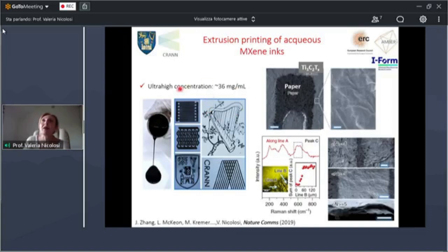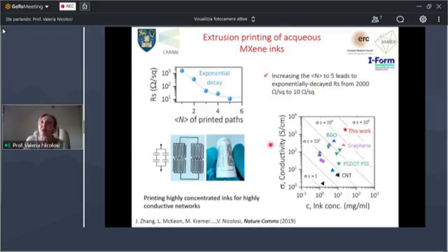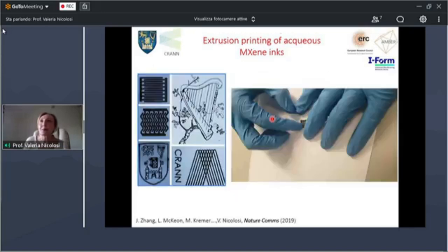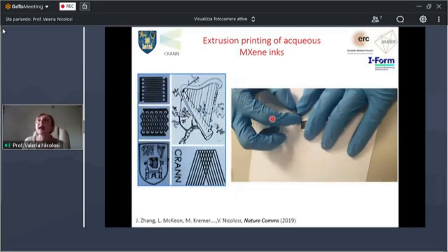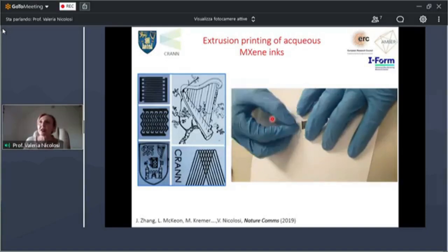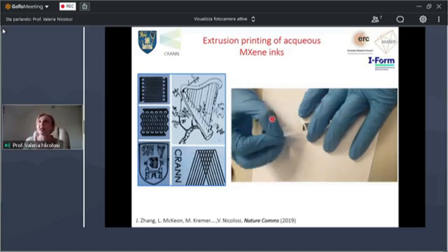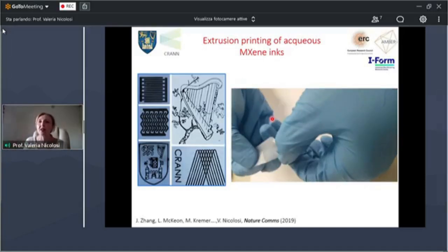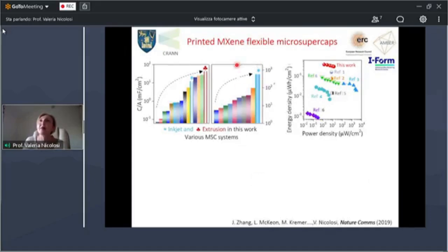And this is an example of the devices that we printed from water by extrusion printing. Again, you can use interdigitated structures. You can print other types of less geometrically rigorous structures. And they really perform, because you achieve very high conductivity with only a few printing passes. The devices are very stable and resistant after you print them. Here is a test by Scotch tape on a device, and you can try to peel off the layers of your device, and you don't get any residual. They're very sturdy.